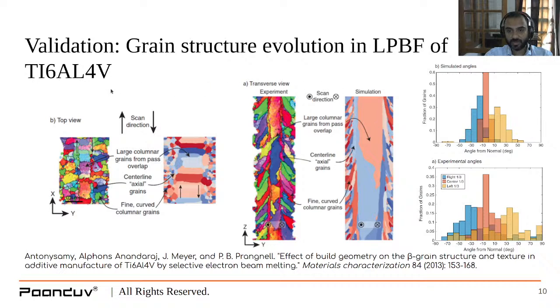In fact, if you look at this in a visual manner, if you look at the transverse view, you will see that based on the scan direction, the laser is hitting into the screen. You can see that large columnar grains are predicted by both simulation and experiment. Some centerline axial grains are predicted by both simulation and experiment, and similarly fine curved columnar grains are also predicted in a very good way. If we move on to the top view, where the scan direction is going up and down on this screen, not into the screen, again you can see large columnar grains, central axial grains, and fine and curved columnar grains, very similar to the experimental photo. The experimental one is the left one in both cases, and simulation is the right one in both cases.